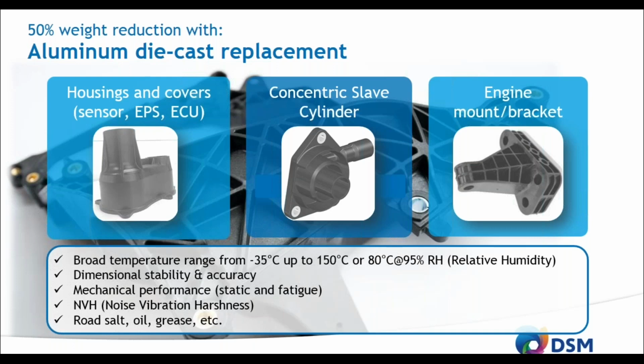These types of structural parts have of course a lot of specifications, and they often have to operate in a broad temperature range from -35 degrees C up to 150 degrees C, and still keep their strength and their stiffness at these high temperatures. Sometimes these high temperatures are not required, and you only go up to 50 or 80 degrees C, but then with a very high relative humidity. Also, if your car is parked in Singapore and you start driving with it, you do not want to have any influence of, for example, moisture on the stiffness of your part. So dimensional stability and accuracy are also very important.